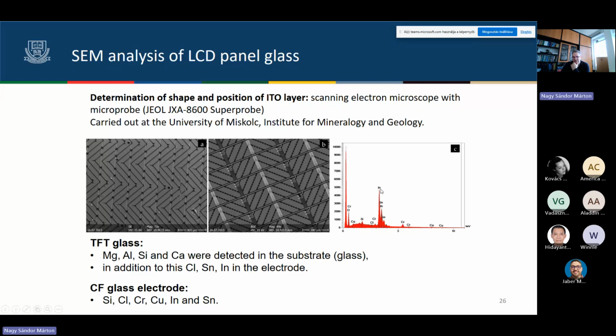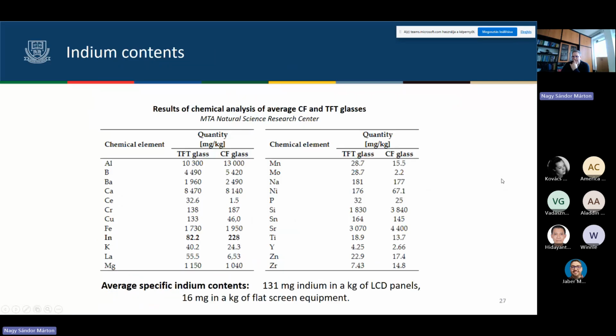Okay, here you can see the measured indium values. Here is the composition according to our measurement of what was found in the TFT glass and CF glass. The average specific indium content was 131 milligram indium in 1 kilogram of LCD panels. It means only 16 milligram in 1 kilogram of flat screen equipment. It's a quite small amount.